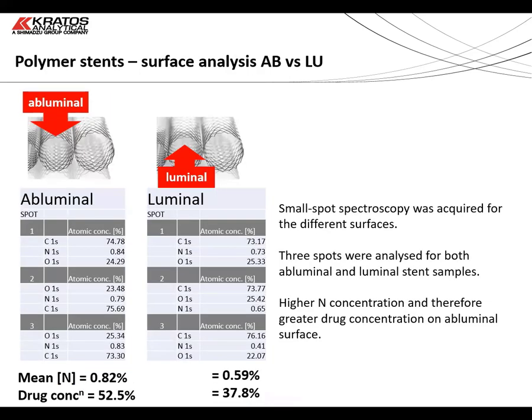Analysis was performed from 3 independent positions on the abluminal or outer and luminal or inner surfaces of the stent material. It was determined that there was greater nitrogen concentration on the abluminal surface relative to the luminal surface, thought to be consistent with the manufacturing process.